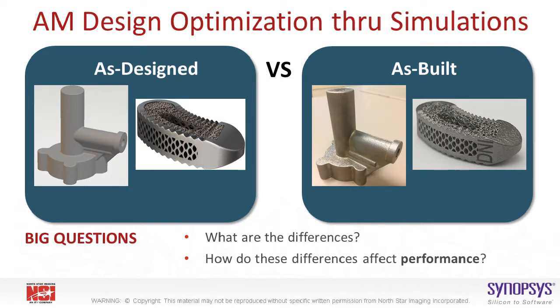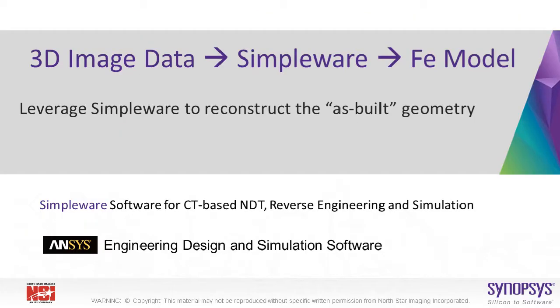There's a significant advantage in performing FE simulations of AM product designs. However, one of the missing components is when I hit print, how does the end result part really compare in dimension, internal integrity, and material properties? CT can be used to provide an as-built model of the part that can be compared to the as-designed model. Once we've scanned the as-built sample, we can take that 3D image data, place it into Simpleware, and then use that in the FE model. So basically, we leverage Simpleware to reconstruct the as-built geometry with a real fine mesh structure.